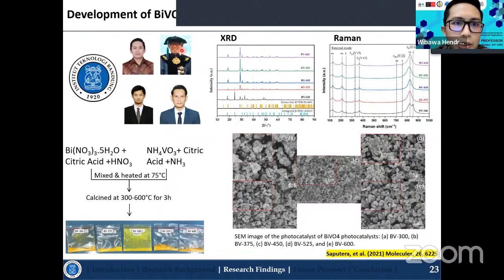Okay, so the next one is the POME degradation, palm oil mill effluent degradation. So previously we focused on textile wastewater. So I also developed a catalyst other than titanium dioxide. I tried to develop a bismuth vanadate photocatalyst. So this is the method where we mix bismuth nitrate, citric acid, and nitric acid, and mix it with ammonium vanadate and also citric acid as well as ammonia. Mix it and heat it at 75 degrees C and calcine at different temperatures.